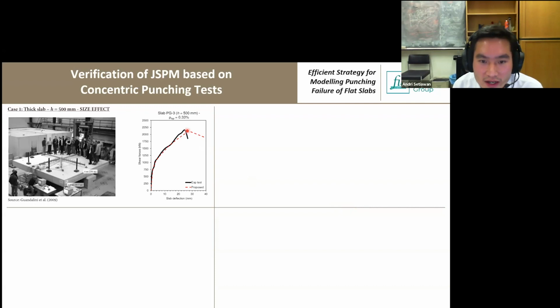In the graph here, the black curve is the test and the red curve is the model that we developed. We can see that the load-rotation response is captured nicely, and also the occurrence of punching. Because the failure criterion that we employ already considers size effect, we are able to capture the punching of these large slabs accurately.